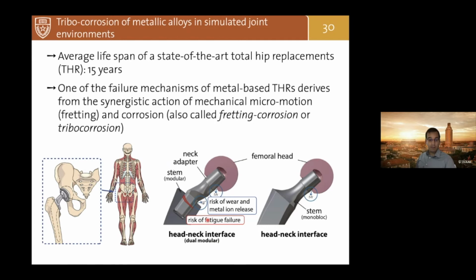The failure mechanism that limits the lifespan of these replacements is actually deriving from failure of these multi-component parts, due to the coupling between sliding or mechanical micromotion and corrosion. That's what is called tribocorrosion.